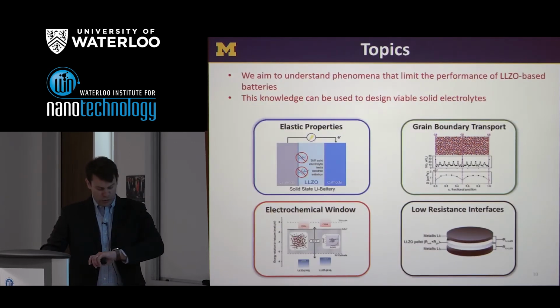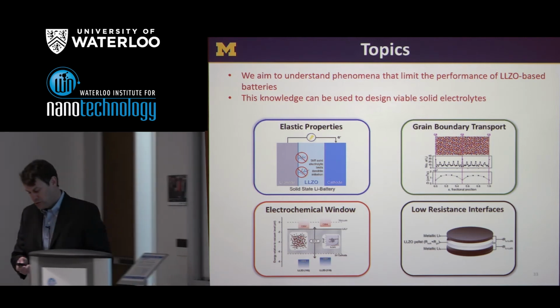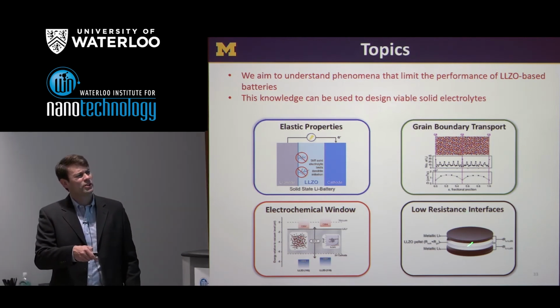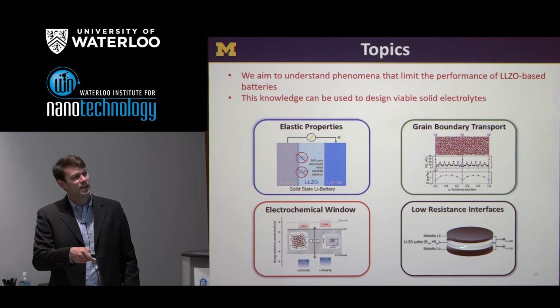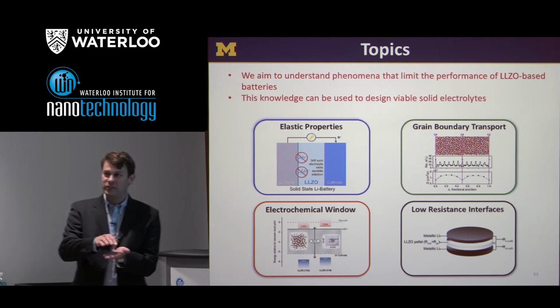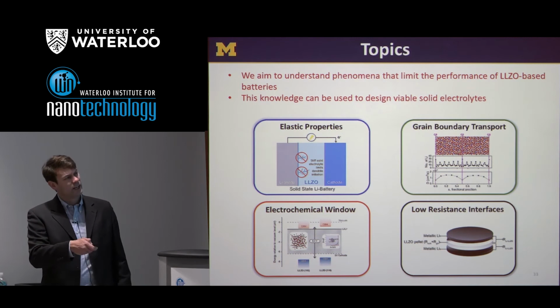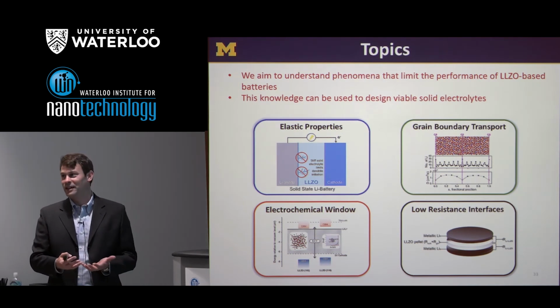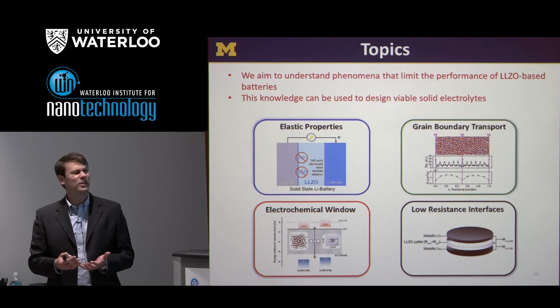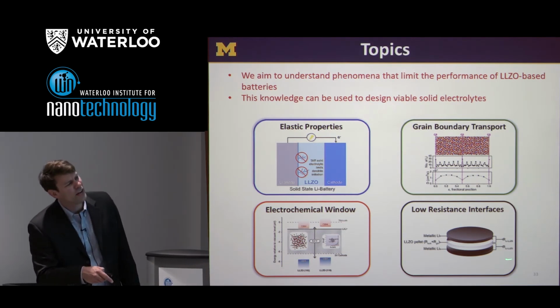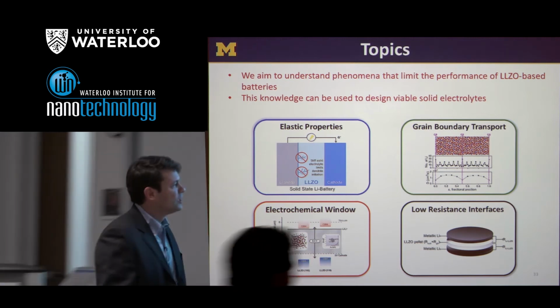Okay, so in the last 2 minutes of my time, let me tell you about some very new work which is not yet published, focused on low resistance interfaces. So I think it was Linda who used the word Oreo cookie before to describe these lithium solid electrolyte lithium sandwiches. And what we're interested in here is trying to put these cells together in a way where the resistance between the lithium and the LLZO is rather low. Ideally, we'd like it to be as low as it could be in a liquid electrolyte. And so we're focused on this value you see right here. This is really small. But basically, this says the resistance of the lithium LLZO interface, and there's 2 of them in this cell.